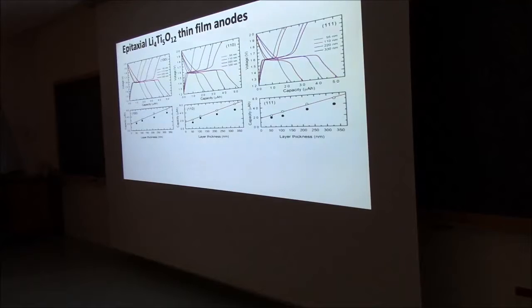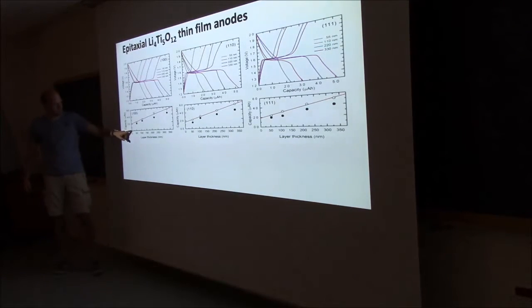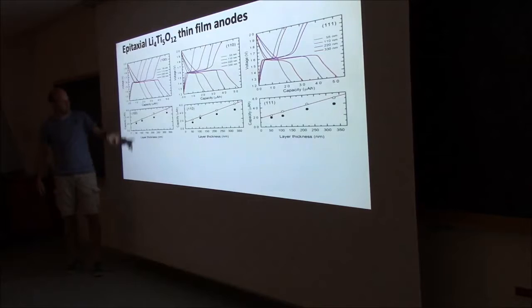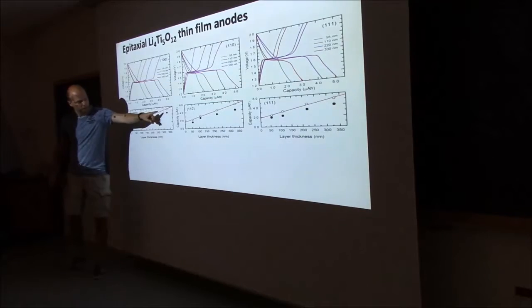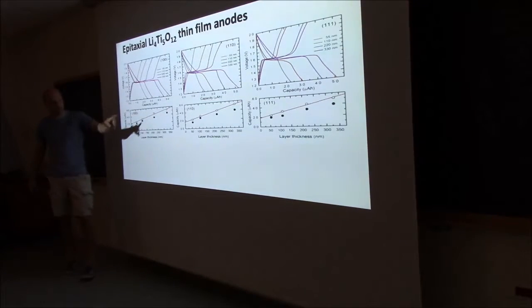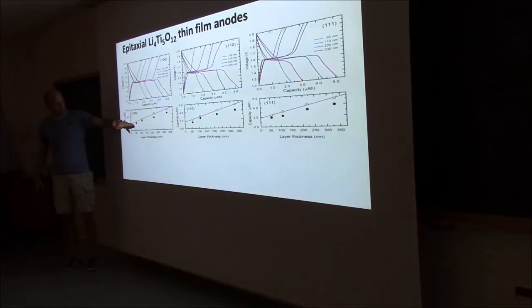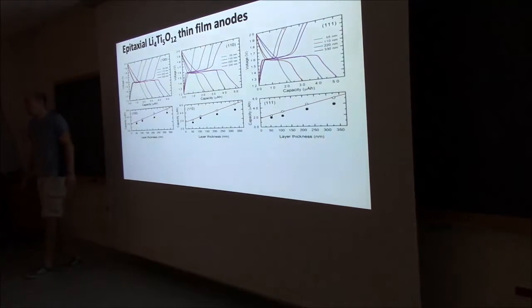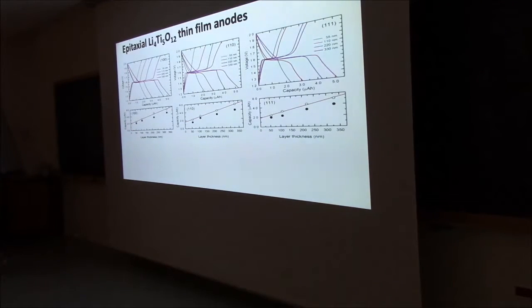The thing that we could do with thin films, which is normally not possible, is play with the thickness. And what you see here, I won't go into detail of all the different measurements, but what you see here is the thickness. This is for the 100 orientation. And then you can see the numbers for charging and discharging, which is going up. But you can see there's a linear dependence, and that's happening in all of them. But there's always an offset over here. And that offset is the amount of capacity which is stored at the surface.